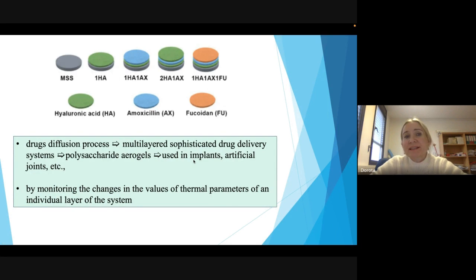And what samples did we analyze? As I already said, they were multi-layered samples made of polysaccharide aerogels, used as sophisticated drug delivery systems. We analyzed a two-layered system that consists of hyaluronic acid and amoxicillin as the antibiotic, whose diffusion into the layer below we would like to examine. Another one was two layers of hyaluronic acid with an amoxicillin layer between them. The last one of interest consists also of three layers: hyaluronic acid, amoxicillin, and fucoidan.